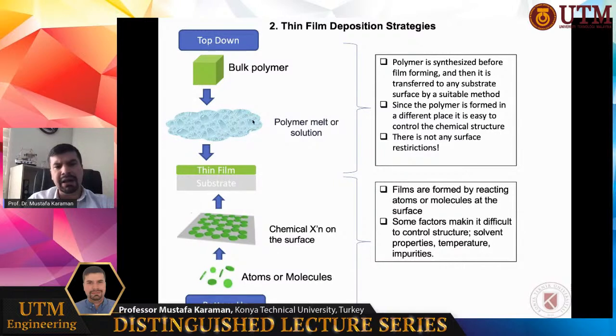Here, since the polymer is synthesized before the coating process, it is easy to control the chemical structure. You don't depend on the surface. There is not any surface restriction. This is an advantage, but the disadvantage is that you need to have a second stage to coat this material on the surface, which is a big problem.